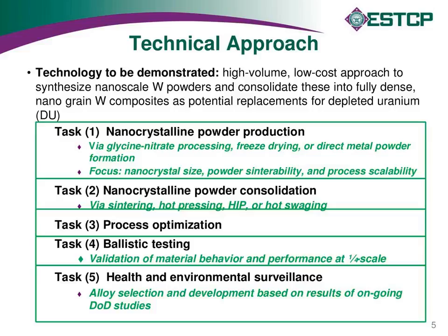And then task 2 was looking at how do we consolidate these materials. That's always been the big trick with these nanocrystalline materials, is producing a fully dense product without growing the grain size too much in the process. And again, remembering that slide about the nanocrystalline iron, it looked like around 250 nanometers is kind of the target goal, at least for iron, which is another BCC metal. We probably want to be in that same neighborhood with the tungsten-based materials. So getting to that ended up being our big problem in this project. Getting to that kind of grain size and full density was a real obstacle.